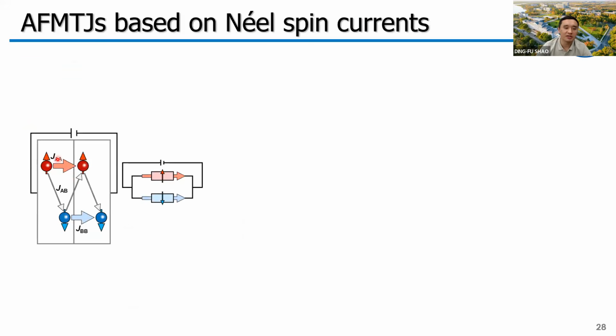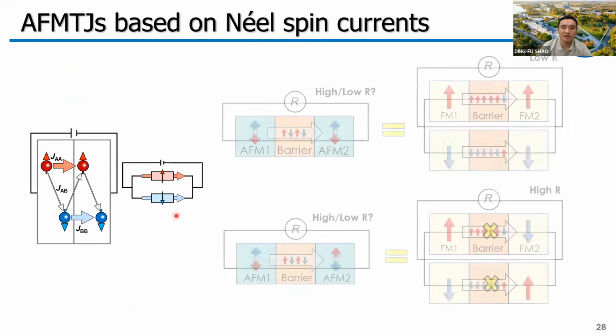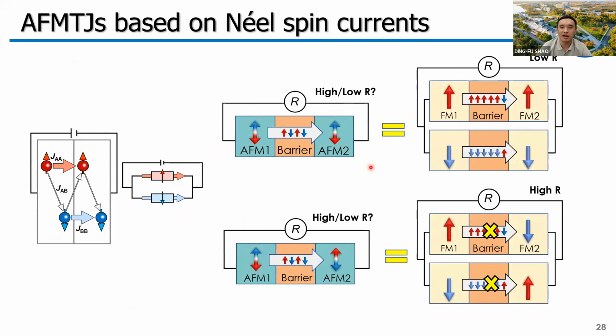So if we can find some antiferromagnetic metal supporting the Néel spin currents, we can use it as an electrode to construct the antiferromagnetic tunnel junction. In this case, we can simply consider the antiferromagnetic tunnel junction as two ferromagnetic tunnel junctions connected in parallel. Therefore, the TMR and the STT are straightforward. And if the Néel spin current flows